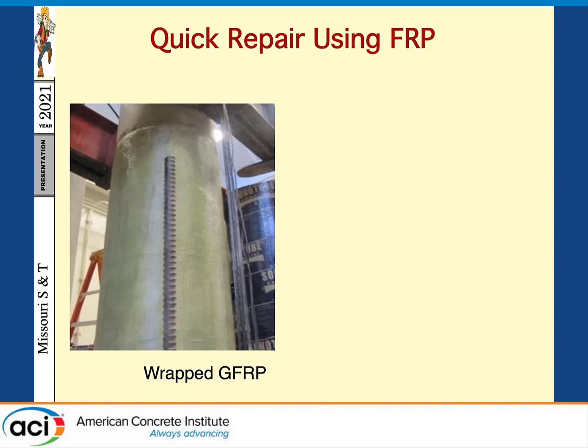And then we applied the 3 layers of glass fiber. So we applied 3 layers of glass fiber, and then those took about 1 hour for applying the fiber. And then, we don't want to wait the full time for curing the glass fiber.